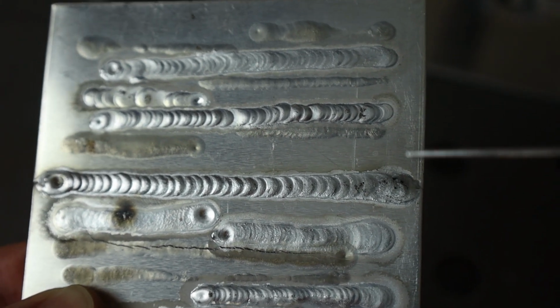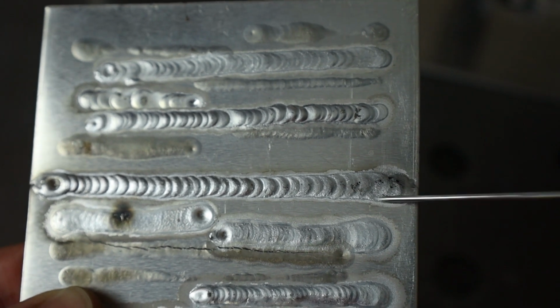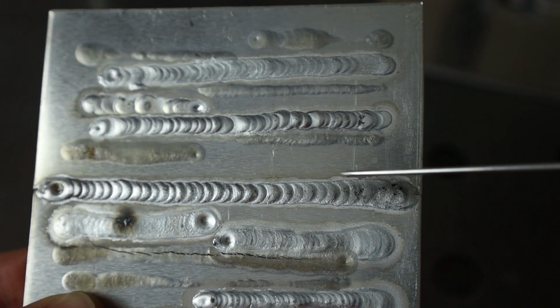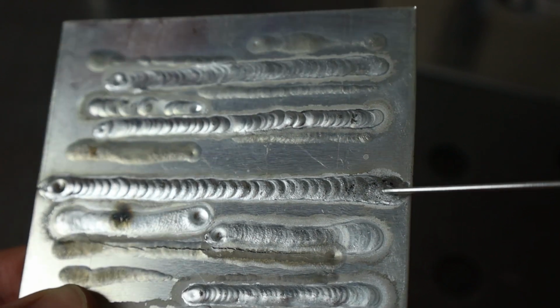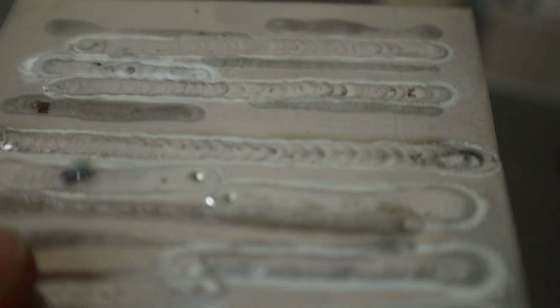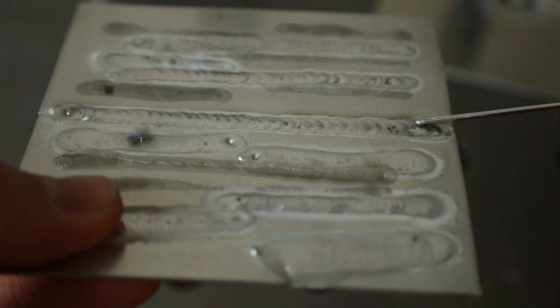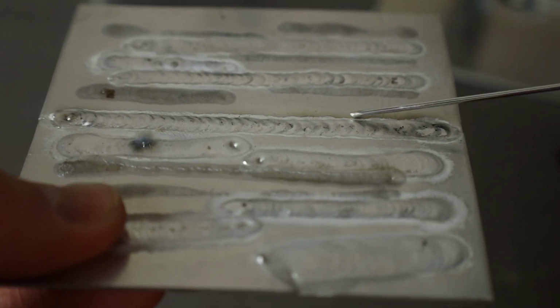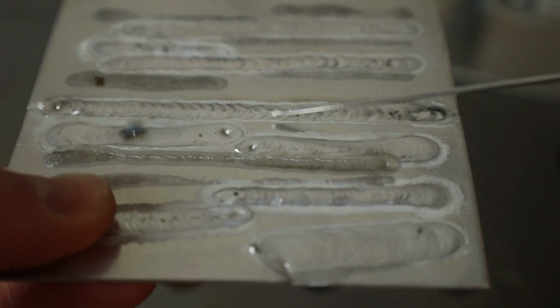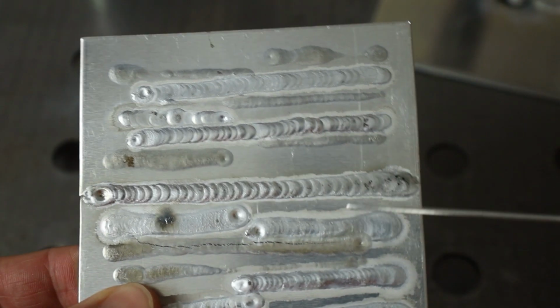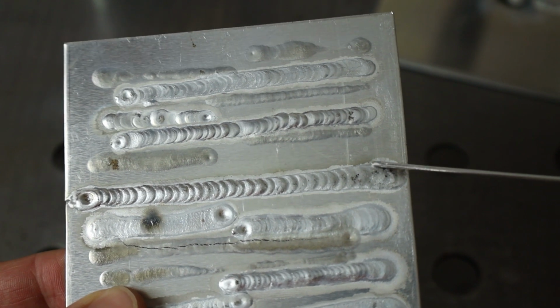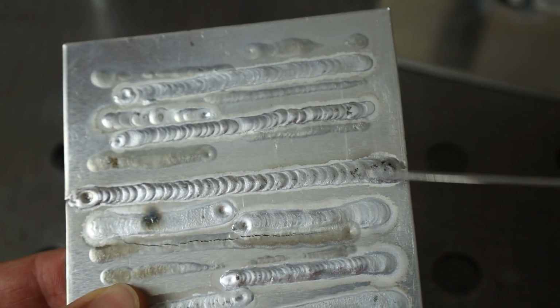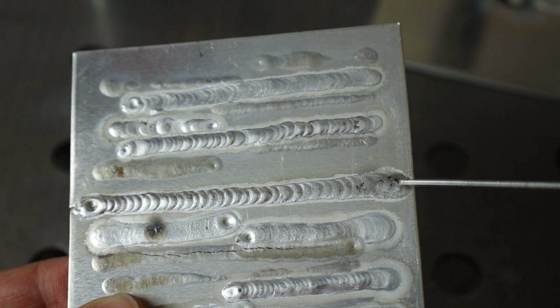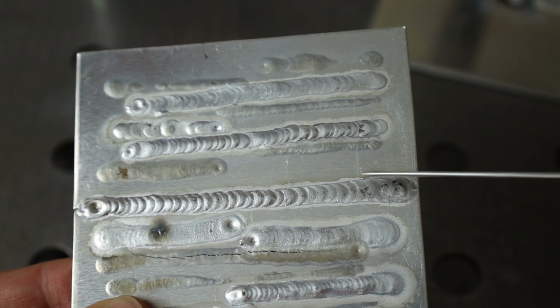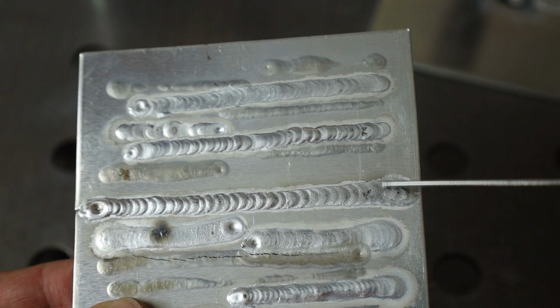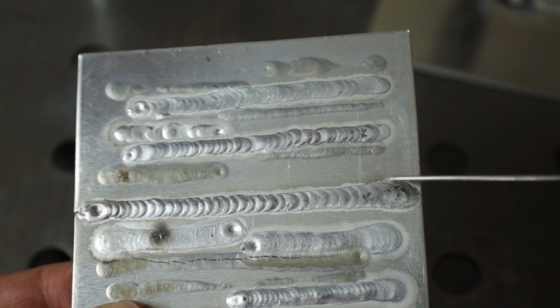I started up the arc, I got my weld pool, and I just took a little bit too long to get going. And I don't know if you'll be able to tell how flat that is. You can see how almost sunk in this is, as opposed to how these have a decent little dab profile for every single one of them. So that indicates to me that I was too hot at the start. Not that I was running too many amps, but that I was moving too slow. I had an appropriate amount of amps here, I just got moving too slow, so the amperage I was feeding into it was just spreading, becoming a big heat sink.